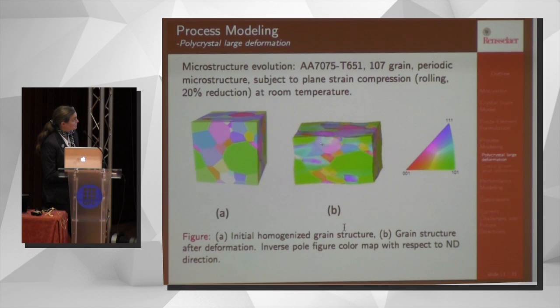And so what you see is that initially each grain has a single color in it, but after deformation, we start to get a range of colors. For example, here we get this white region inside of this originally purple grain. So what's happening is we're getting a cell forming of a different orientation from the surrounding material. Likewise, over here, we see this light blue region and this darker blue region. Here we're seeing this purple region forming inside of this. So we're seeing the grains breaking up, and with those new grains, we have misorientation as we go from one region to the next.